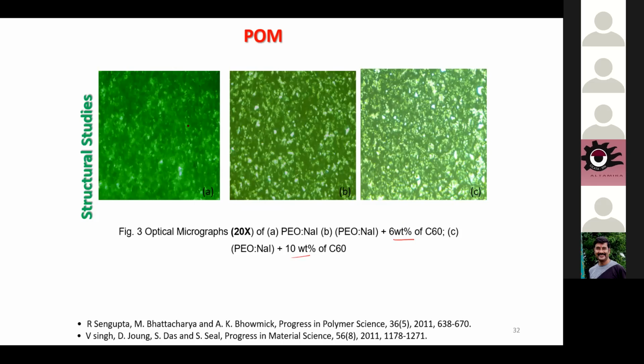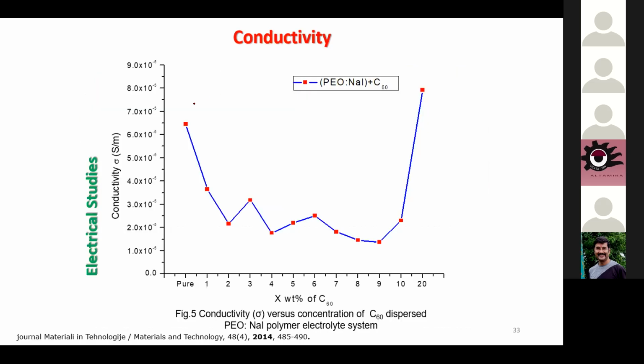So this is the conductivity, somewhere maybe around 6.4, I think, into 10 to the power minus 5 siemens per meter. But as we disperse the first 1% of the Fullerene, it suddenly drops to somewhere around 3.4, 3.6, some 10 to the power minus 5. This decrease in conductivity is maybe due to the increase in the crystallinity initially. But on further adding or dispersing the filler into the polymer, conductivity starts increasing.